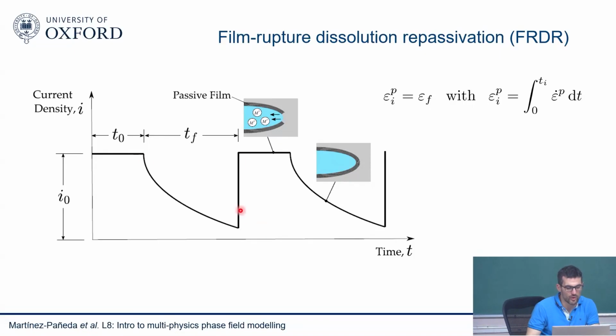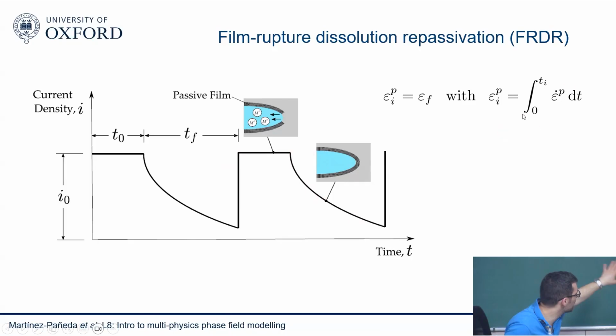This is what this integral represents, right? So we rupture the film. Here we rupture the film. We start depositing a new film, but this new film has not seen the previous loading history. So what matters for this new film is the strain since we start depositing the film. So this is a cyclic process. And then how quickly the corrosion will progress will depend on your loading rate, how quickly you apply your load, how quickly you accumulate that critical strain over the new film, versus how quickly you repassivate that film. That is the idea. So it's an interplay between passivation and straining kinetics.